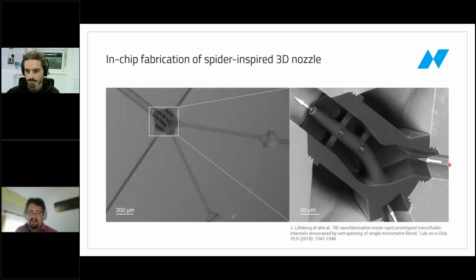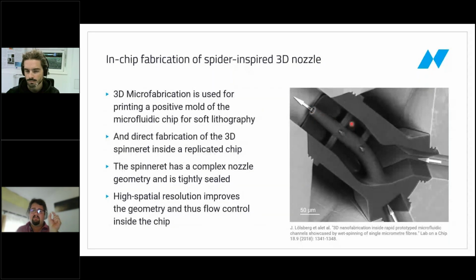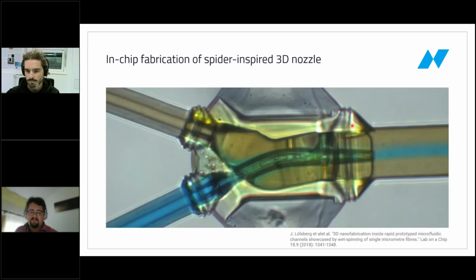In this case here, the customers printed this 3D microfluidic part into the channel in order to combine the flow from this and from this channel into a third channel. And the content of this channel is actually injected through this tiny nozzle into the stream from the other channel. And this is used to make a very thin thread of material, which is built when the two materials come in contact in a very controlled manner in this microfluidic chip. And if you just fill it with painted water, just to visualize the process, you can see here that this actually works. And with this, I come to the end of the introductory part, and we'll see each other later. And for now, I hand over to Severin.